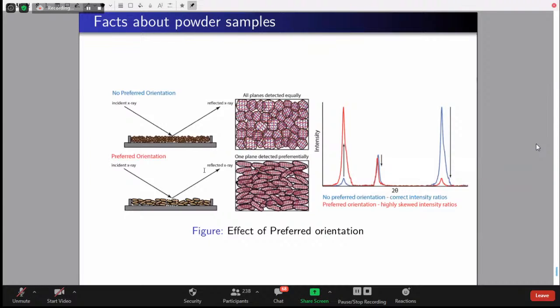Your sample is oriented. You see, sir, here in the cartoon I have shown, these are ground particles, which are almost like spherical. Whereas here, these particles are grown like bananas. They are elongated ellipsoids, which could be because your material is growing like that. That is a material property, which we can't change anyhow. When we do this solid state reaction and other things, they have grown like this. So this is the shape property. If you grind them properly, a little more grinding, and the preferred orientation goes away, that is fine, no problem. But even after grinding, if they are growing in only one direction, that is a property of your material. So you have to interpret the material growth in one particular direction only.